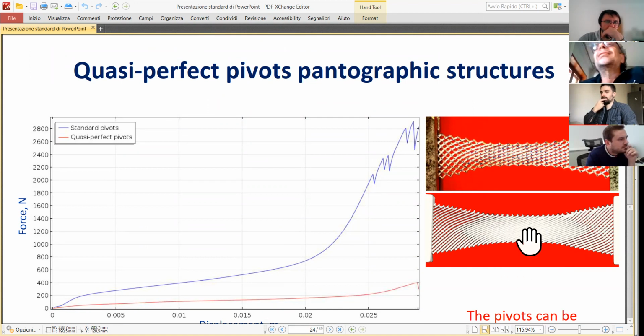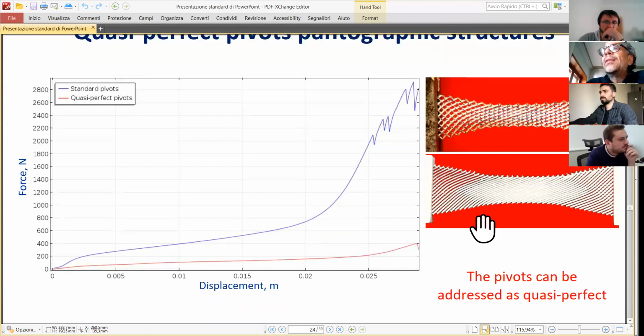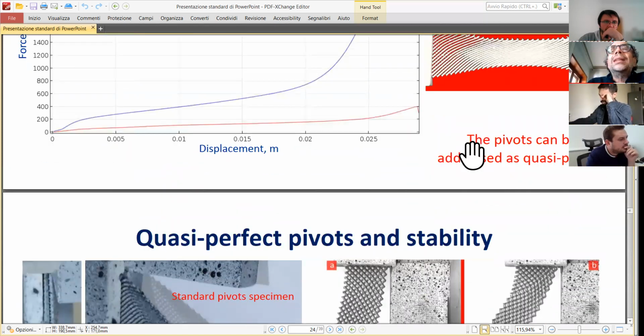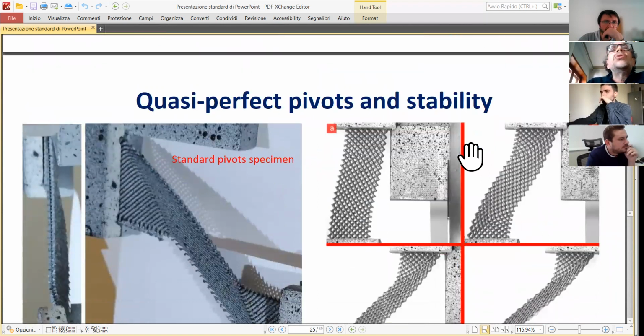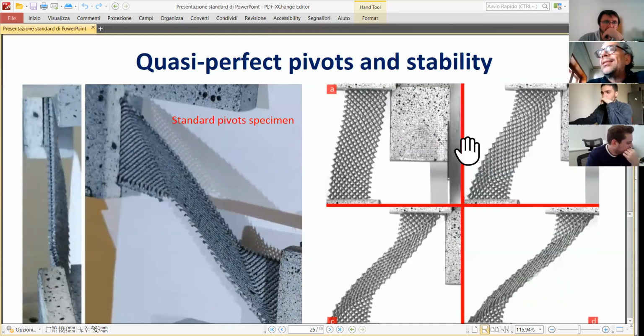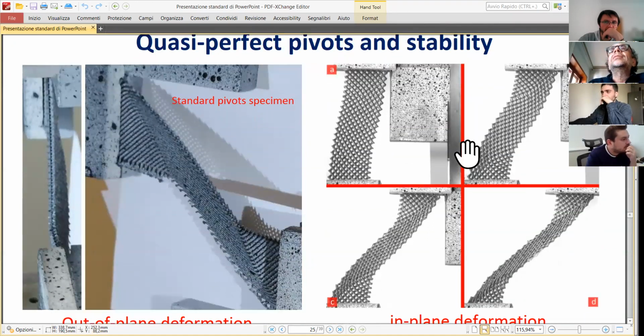So the beams are touching one another so that you have a stiffening of your material. So you have a kind of material which has a stiffness in a certain deformation regime, and another much higher stiffness in another deformation regime. If we manage to design pivots and the structure in an optimal way, and I have partial results in these aspects, then we will have invented the two-phase material which we are looking for. First phase, second gradient; second phase, first gradient material.